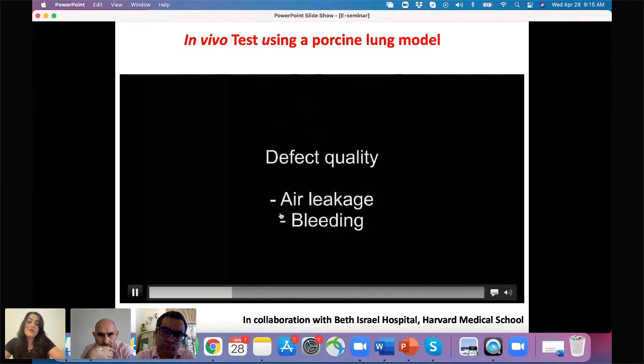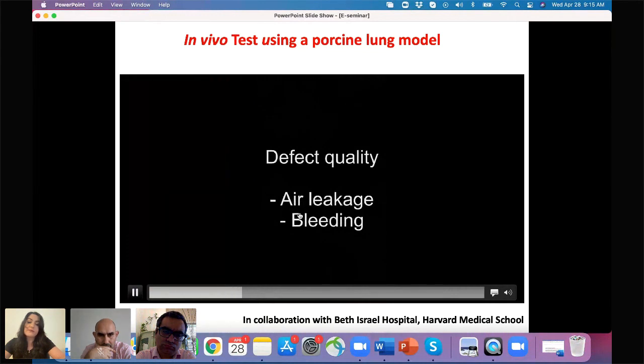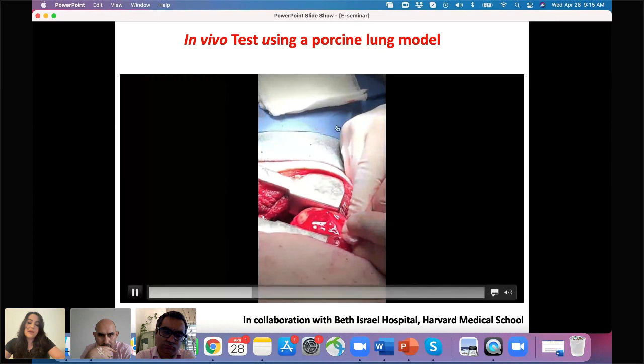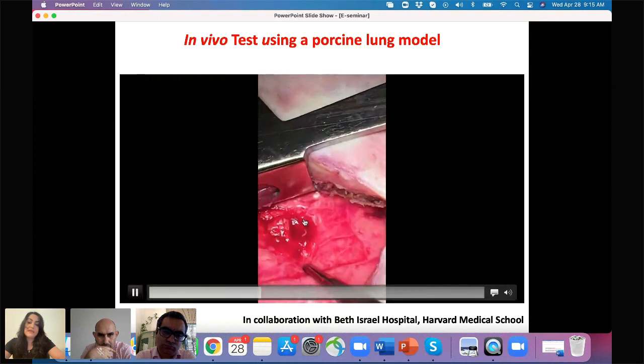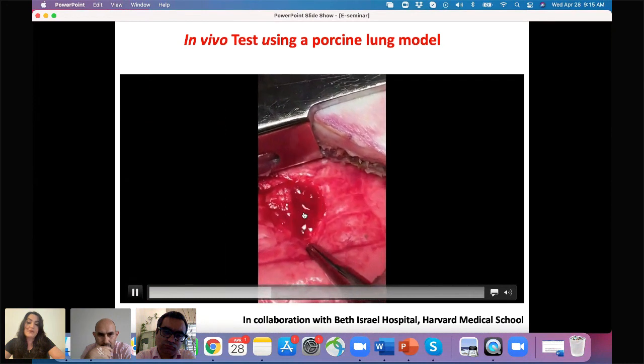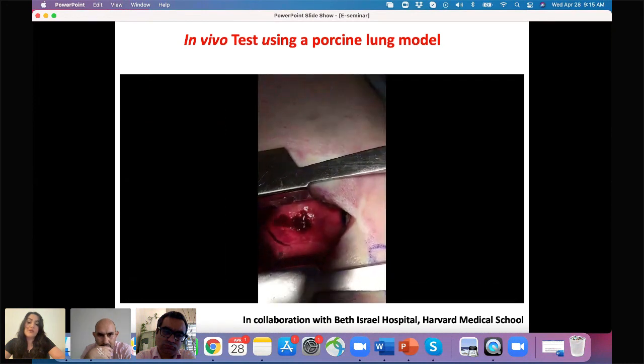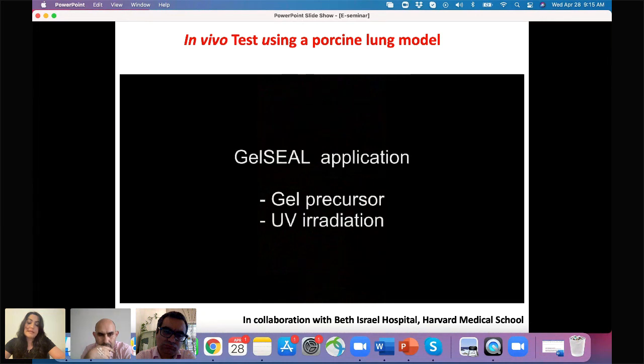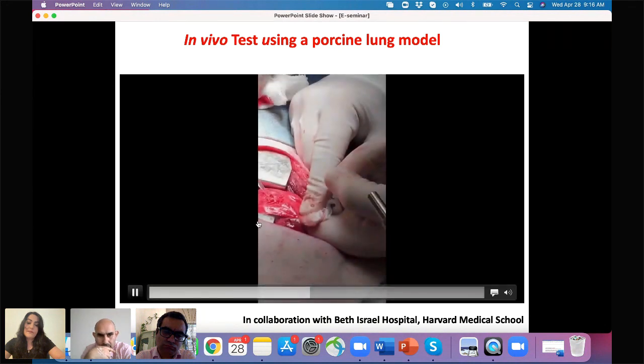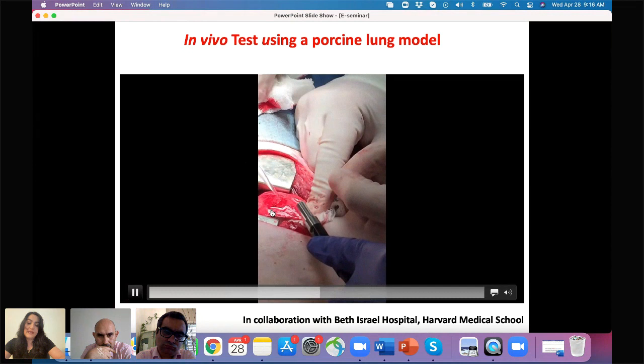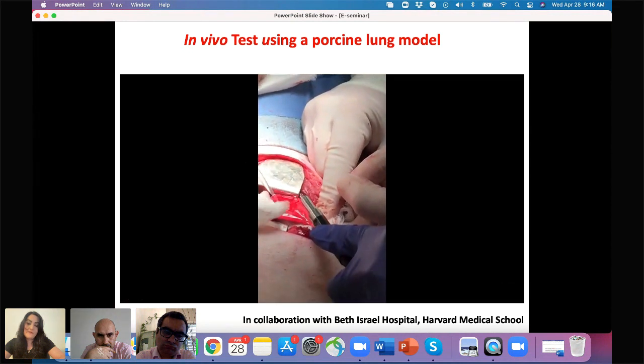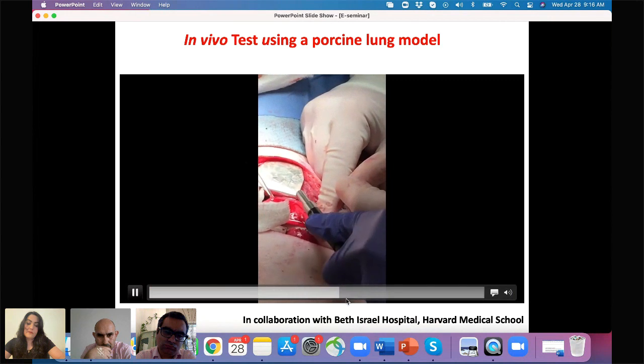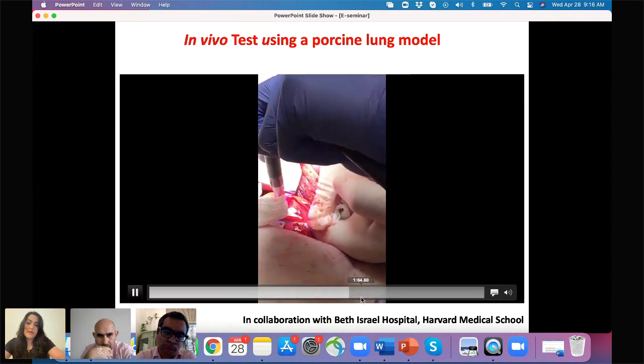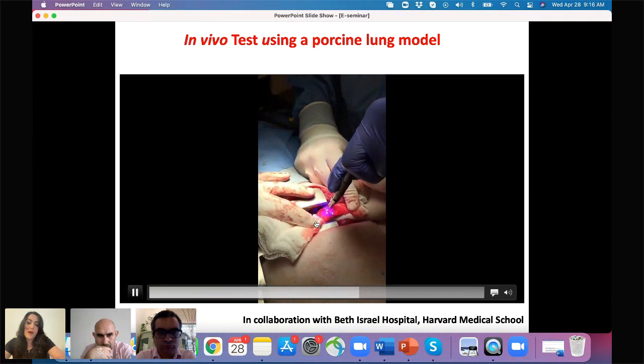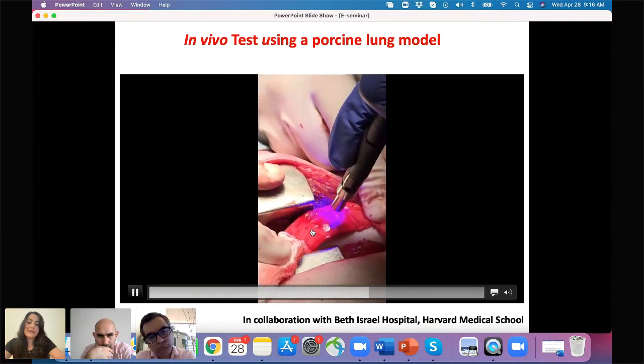And here is the video showing that the defect was created on the lung. And then we check the quality of the defect. After we observe bleeding and leakage from the defect side, we apply our hydrogel. So the hydrogel was applied as a precursor solution. And once we apply it on the lung, we cross-link it by applying light. Okay, so this light exposure for less than 1 minute solidified the hydrogel on the surface of the tissue.